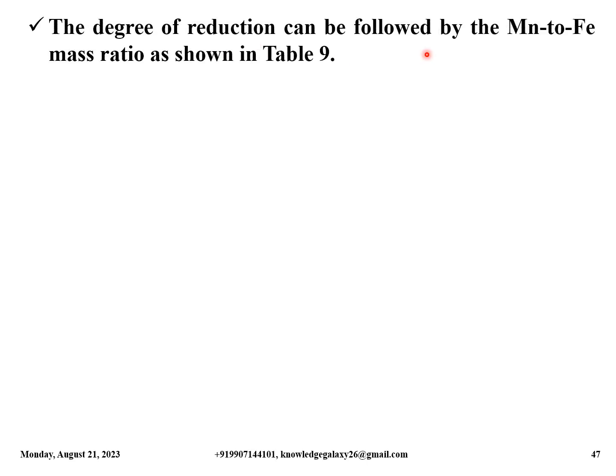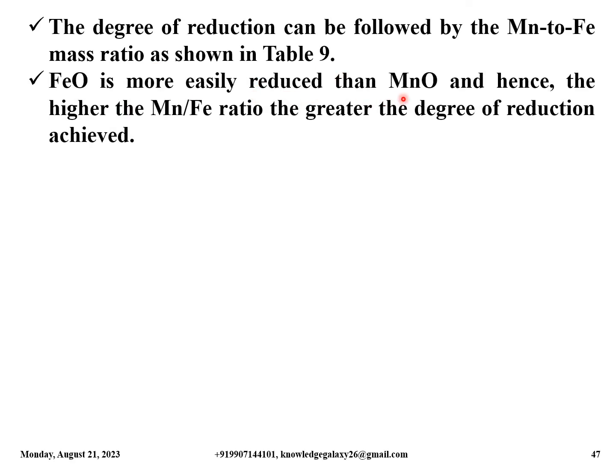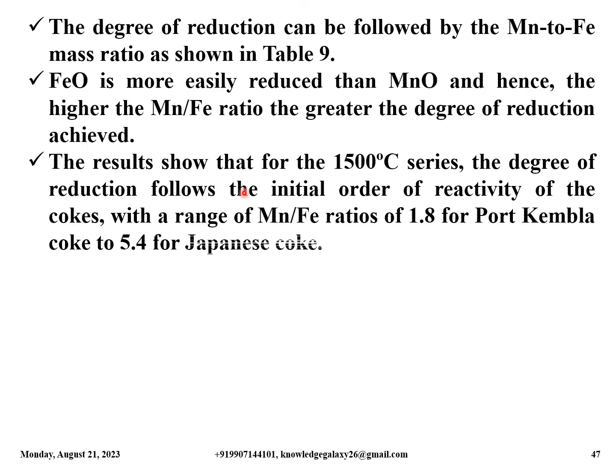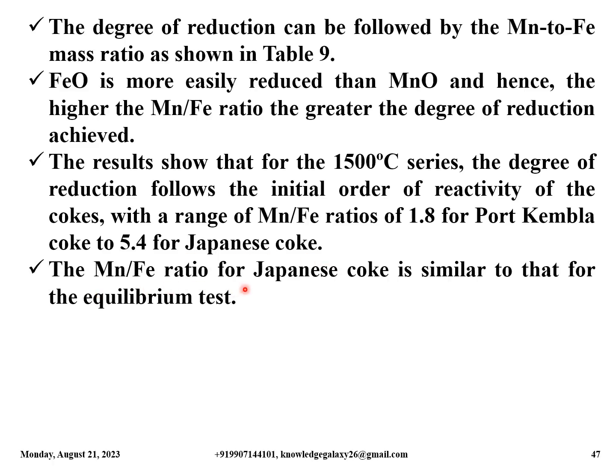The degree of reduction can be followed by the Mn to Fe mass ratio as shown in table 9. FeO is more easily reduced than MnO, and hence the higher the Mn by Fe ratio, the greater the degree of reduction achieved. The results show that for the 1500 degree Celsius series, the degree of reduction follows the initial order of reactivity of the cokes with a range of Mn by Fe ratios from 1.8 for Port Kembla coke to 5.4 for Japanese coke. The Mn by Fe ratio for Japanese coke is similar to that for the equilibrium test.